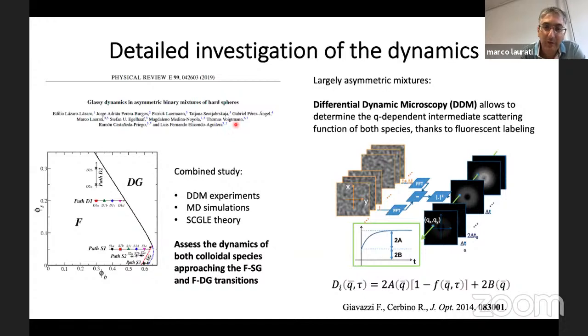But essentially, this is a work that took some time, also because it involved a lot of people, as Stefan was already mentioning. It is a study that combines different experimental, simulation and theoretical results, which assess the dynamics of both colloidal species in the mixture while approaching the fluid to single glass transition and the fluid to double glass transition in the system that I already mentioned in the previous slides, which is this mixture where the size asymmetry is basically 1 to 5 between the small particles and the large particles.